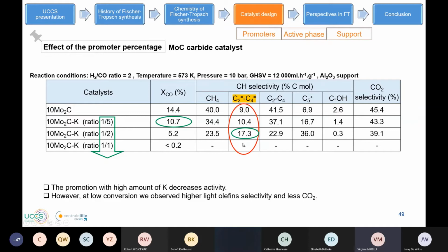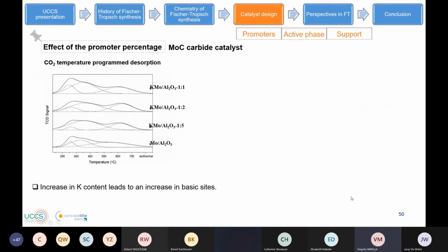So with low conversion, we observe higher light olefin selectivity and also less CO2. We also studied the CO2 temperature-programmed desorption, the basicity of this catalyst, and we observe that an increase in potassium content increases the basicity of the catalyst. The more basic sites we have, the less conversion we have.